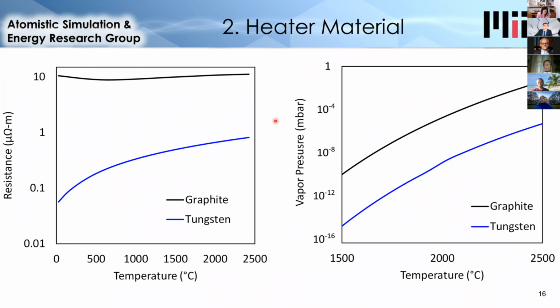Now, in selecting the heater material, there are really only two material candidates that conduct electricity and remain solid at high temperatures above 2000 Celsius, and these are graphite and tungsten. There's two material properties I'm showing here that can be used to try to pick a heating element material. The first is the resistance. So for a heater, you want kind of a medium resistance. It needs to be resistive enough to generate heat, but not so resistive that no electricity can flow. And so tungsten and graphite resistance values are both tolerable.